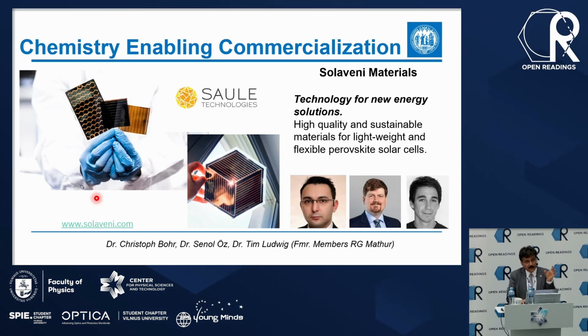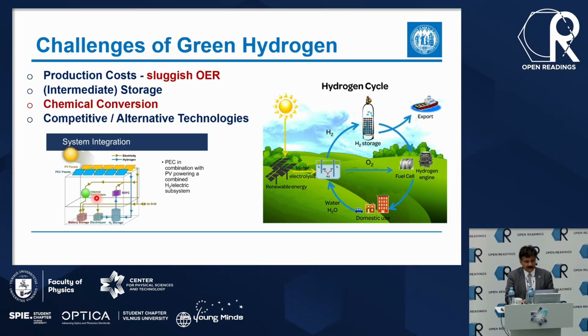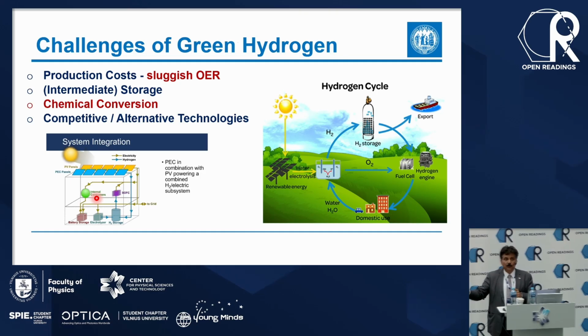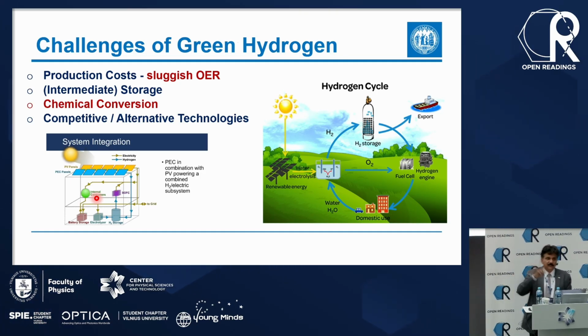So this PV setup can also be used for electrolysis. But still, there are 2 major challenges of green hydrogen. One is the other half of the reaction, because in hydrogen evolution, people think only hydrogen is coming out, but you have 2 reactions. When you split water, you are creating hydrogen and half a mole of oxygen. And the oxygen evolution reaction is actually more important, because that's a 4 electron transfer reaction, and if it is slow, automatically your hydrogen evolution will be slow.